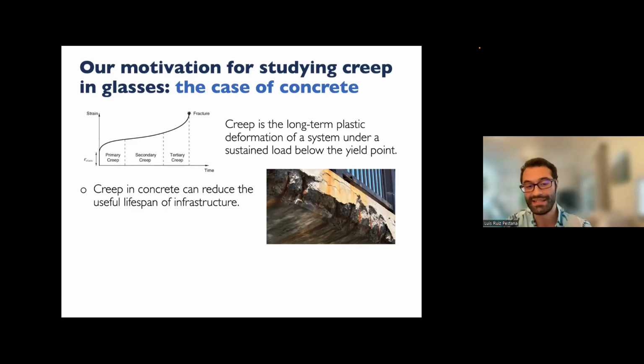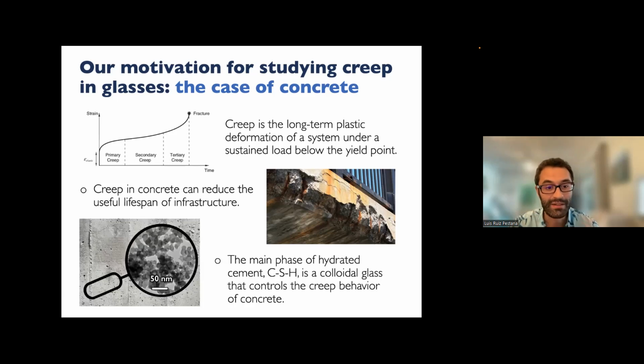And it's not that creep just leads to catastrophic failure, that it can, but even mild creep can lead to cracking that accelerates degradation processes. So it's a very important process that costs millions of dollars in repairs. So creep in concrete is governed by CSH. Calcium silicate hydrates are the main phase of hydrated cement, which is the glue in concrete. And it turns out that CSH is a colloidal glass. And the creep behavior depends on the relaxation of this glass under sustained loads. So this is our particular motivation.